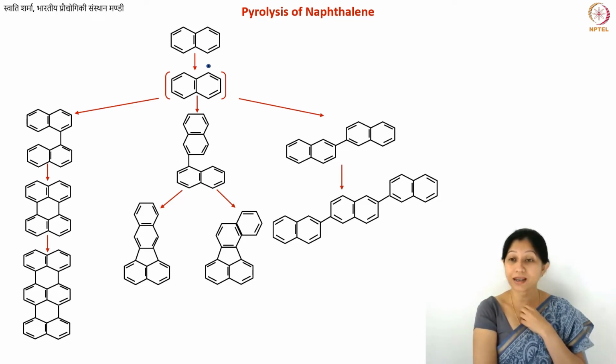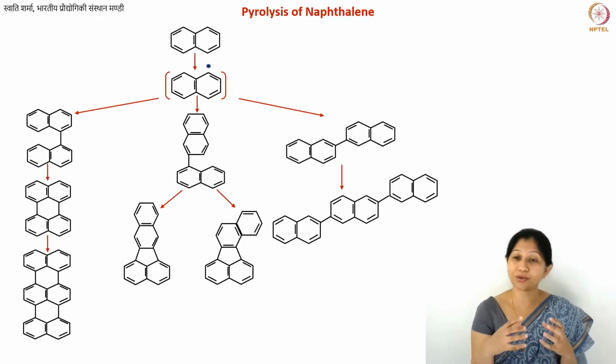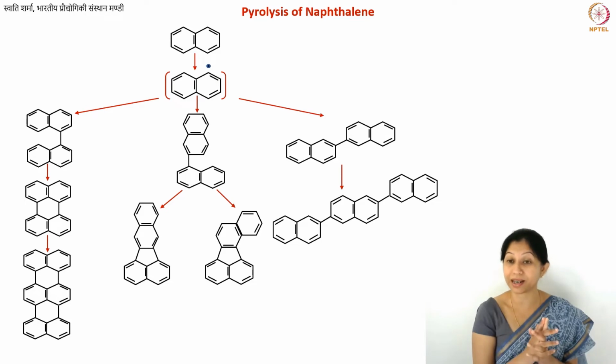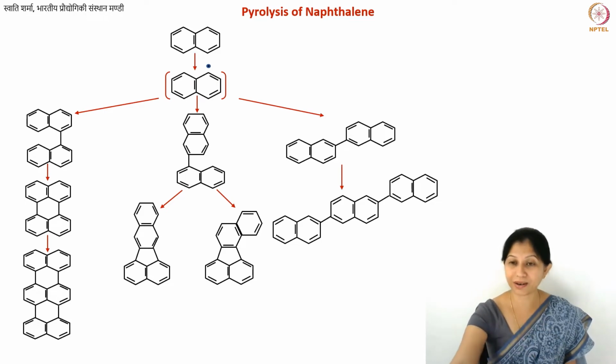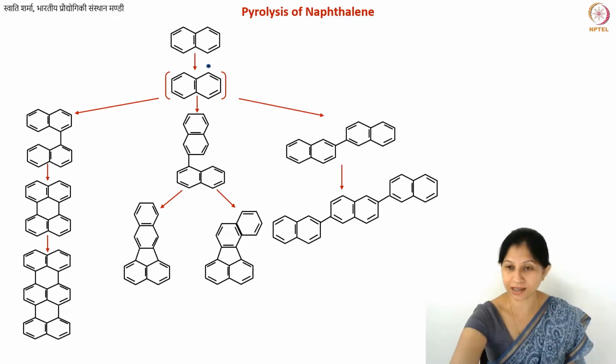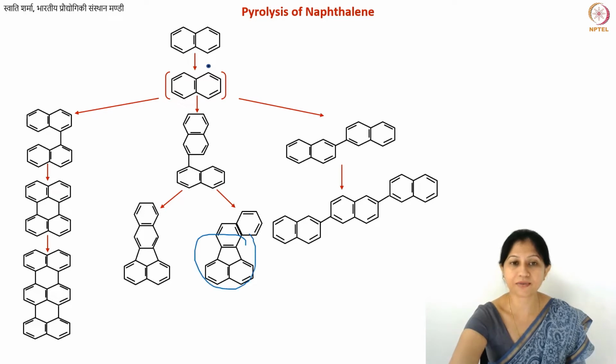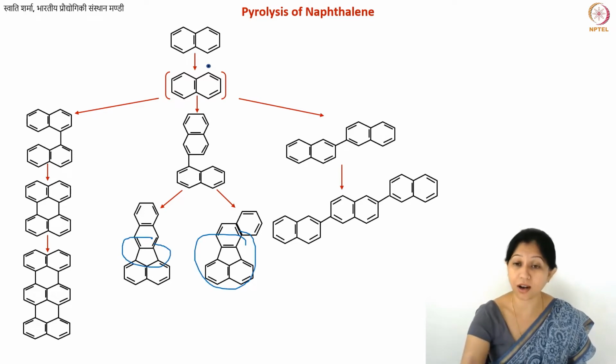But when you actually perform the pyrolysis, it has also been shown to yield some fullerene molecules, completely spherical Buckminster fullerene-like molecules. So here you can already see that when you pyrolyze your naphthalene, you are getting cyclic structures, but you also get these 5-membered rings. Here and there you have such structures, not all of them by the way.